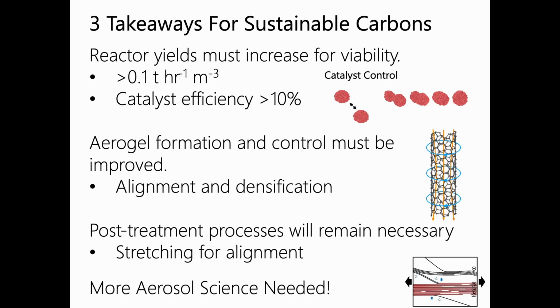So I'll end with maybe three takeaways for sustainable carbons. I think for this to really be viable, where the climate cares, not just that industry cares, we need to get reactor yields up, and they need to be substantially higher than where they're at now. About a factor of 10 would probably put us in good stead, and ultimately with the goal of getting them up by a factor of 100. I think the way to do that is by improving catalyst efficiency, getting better at making catalysts and keeping them from agglomerating.